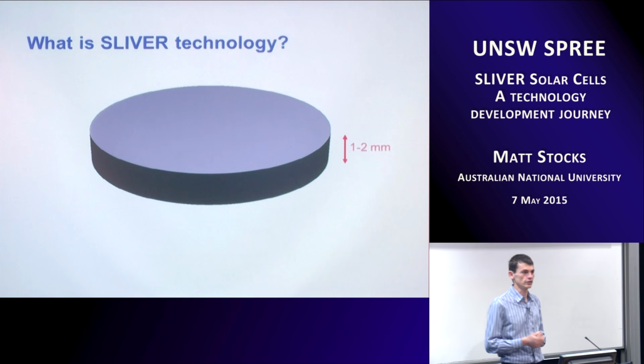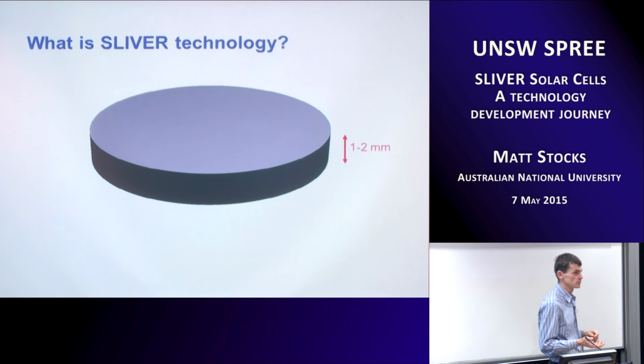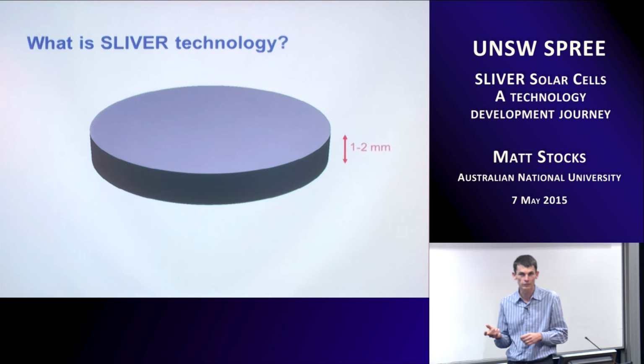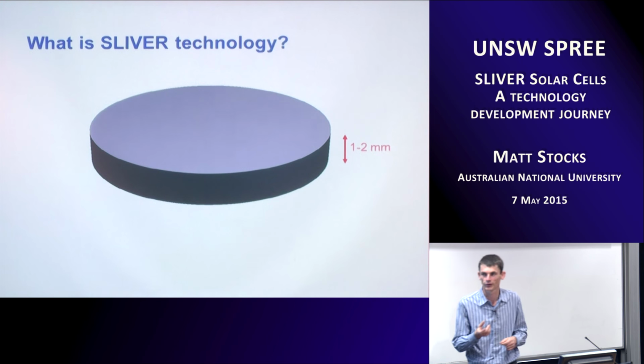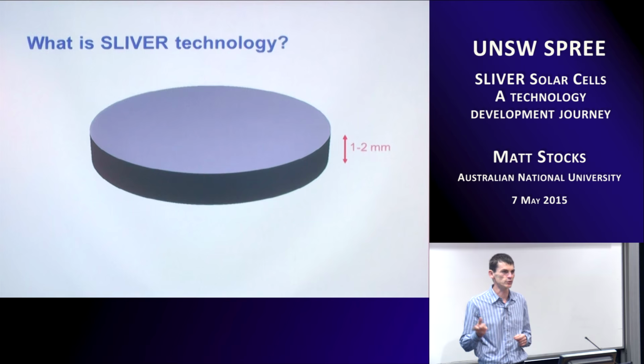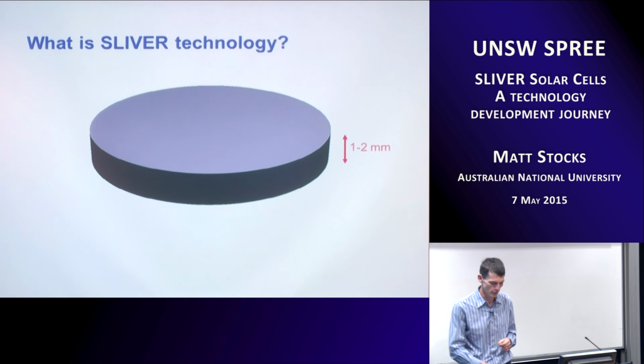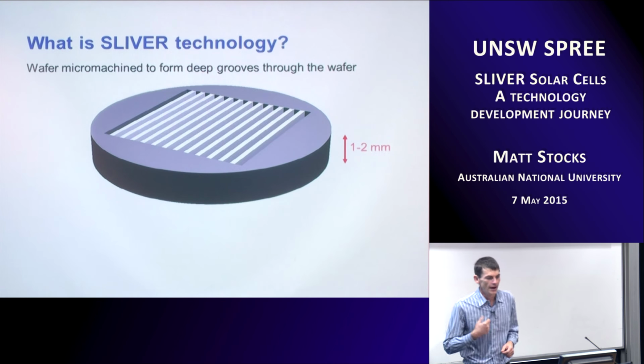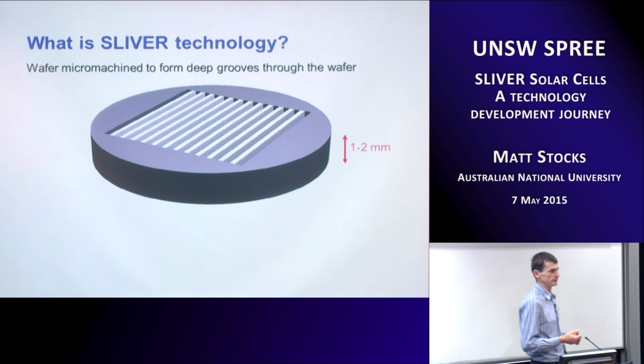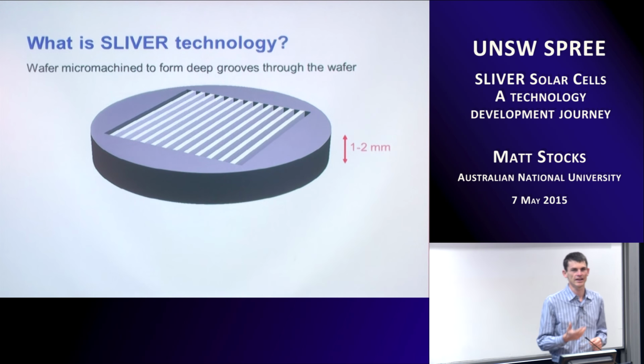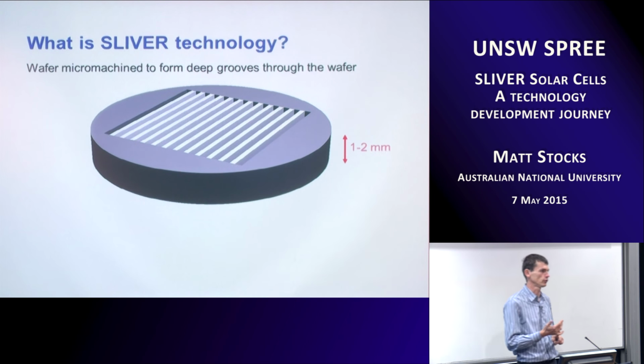So what we do with SLIVER technology is we take a standard CZ wafer, except instead of being 150 microns to 200 microns thick as the solar industry is in today, we're taking something which is 1 to 2 millimeters thick, so quite a thick wafer. And then what we're doing is we're micromachining it. And what we're taking advantage of is silicon has this amazing property that in an alkaline etch, one of the crystal planes etches much, much more slowly than the other crystal planes.